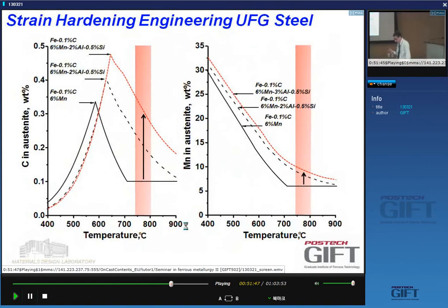For me, it's a technological constraint. Yes, this is the temperature at which continuous galvanizing lines operate when they anneal cold rolled material. We're interested in this temperature range because a steel producer who makes automotive grades does not change that temperature all the time. Yes, you might think that's a stupid thing, but there are many reasons they don't do it. So your furnace works at 800, and your new steel has to be annealed at that temperature, whether or not it's the optimal temperature.